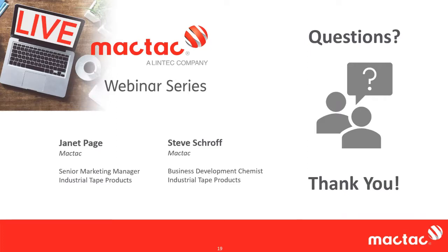I think the second half would be, is it ever as good as a rubber-based adhesive? And the answer there would be no. A rubber-based adhesive is always going to be better on low surface energy materials than even an LSE acrylic. The reason why is that the tackifiers have to be compatible with the adhesive, and the tackifiers that are compatible with acrylic adhesives are higher surface energy tackifiers.